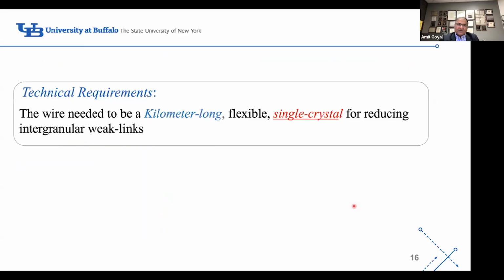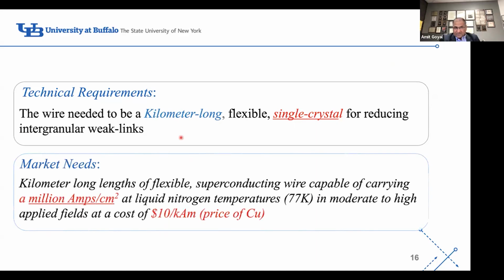So, what do we need? In order to realize the dream of the 1987 Nobel Prize, we needed a kilometer-long flexible single crystal for reducing the weak links in these materials. However, there's a catch. This wire had to be equal to the price of copper wire that you go and buy in your hardware store. The price of copper wire is $10 per kilo-amp meter, which meant that this wire, as I mentioned previously in the hair example that I gave you, you need a critical current density over 1,000,000 amps per centimeter squared.